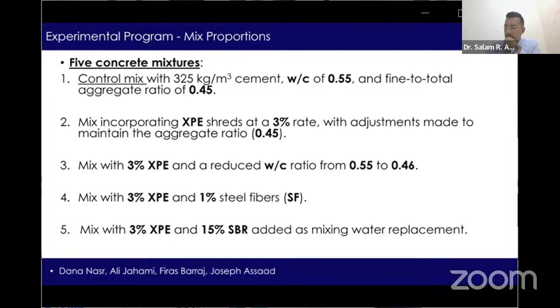The second mix incorporates XPE shreds at 3% rate by total concrete volume. It should be noted that fine and coarse aggregates are adjusted accordingly to maintain a fixed aggregate ratio of 0.45. The third mix is with 3% XPE plastic waste and reduced water to cement ratio from 0.55 to 0.46. 4, mix with 3% XPE and 1% steel fiber by volume. And the final mix consists of 3% XPE and 15% SBR as a mixing water replacement.